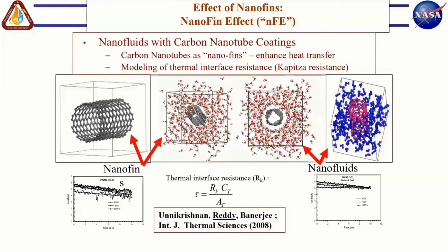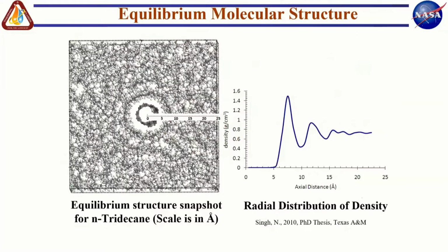And that's proportional to the resistance times the capacitance of your nanofin. And so by using this molecular dynamic simulation, we were able to predict the Kapitza resistance. But once we looked a little closer into this final equilibrium configuration of these molecules around the nanofin, what we notice is right around the nanofin, you form a cluster of molecules that have a higher density. And you sort of see this density oscillation wave that decays with distance away from the surface of the nanofin.